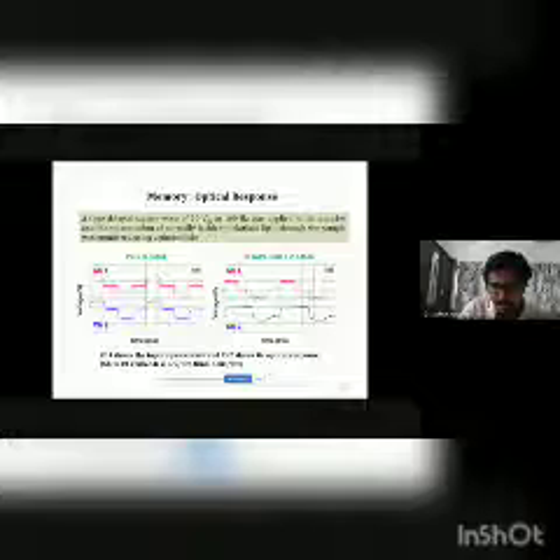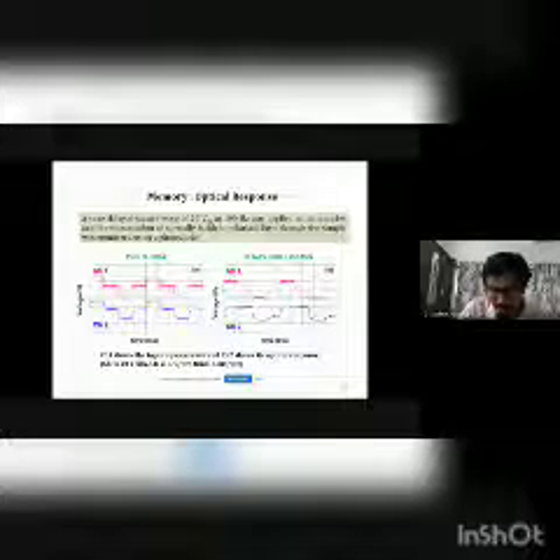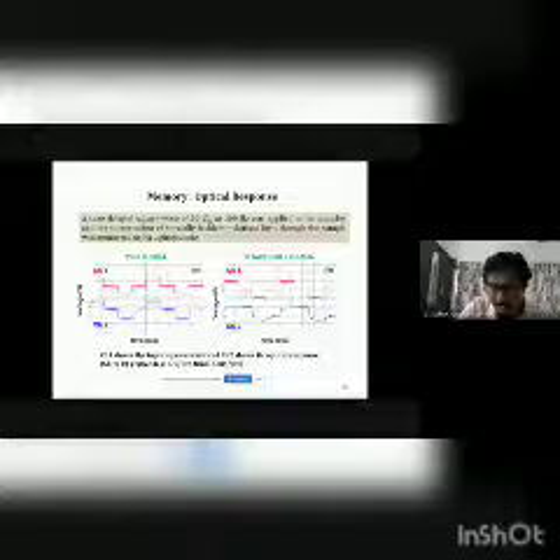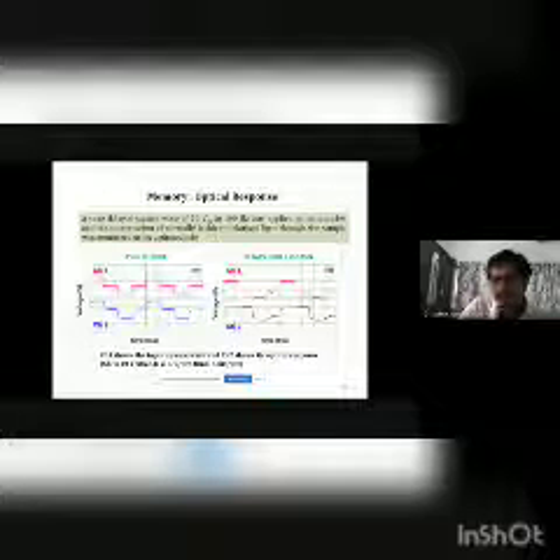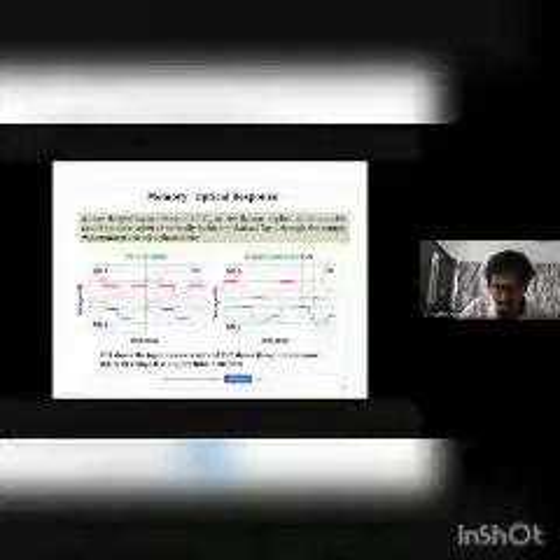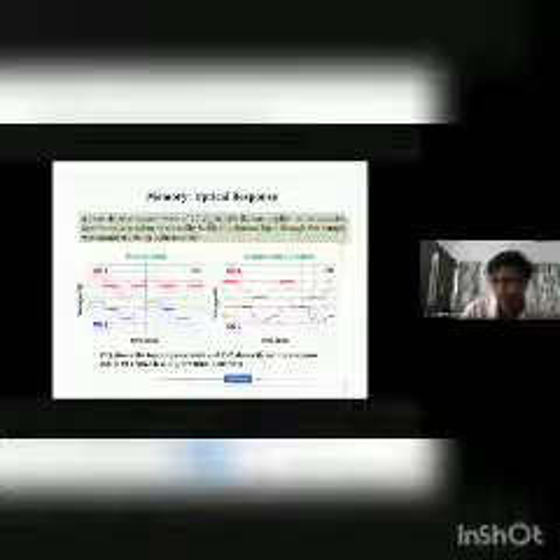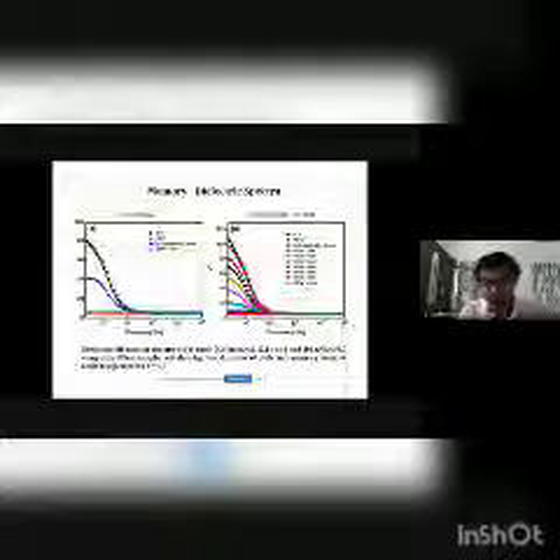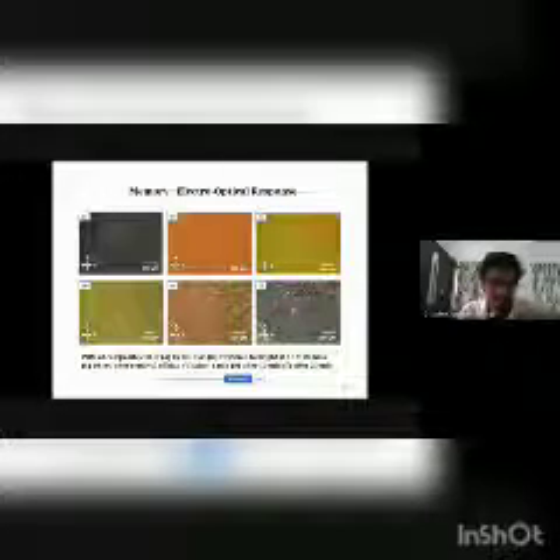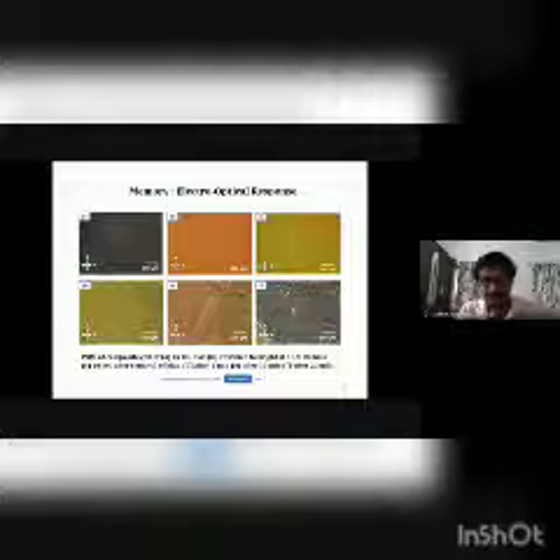In your composite sample, this is the input pulse and this is the output pulse. When your input is switched from 1 to 0 state, the output still remains in one state until another reverse pulse. So this time duration is the memory duration of this type of molecules. In the negative cycle, the memory is slightly distorted due to small alignment and other issues in these molecules. But in the positive cycle, the memory is retained almost every cycle. So from the optical response and the dielectric spectra, as well as from the POM microscopic images, we have concluded that these molecules have optical memory.